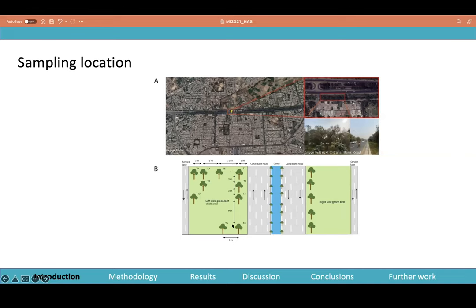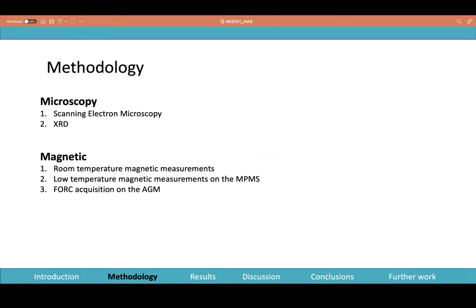You can see the different locations of the trees, but all of them were collected at inhalation height, just because it was easier for me as well to not go through the risk assessments and everything to get a ladder. So the methodology we applied on these leaves was a range of microscopy and magnetic measurements. We started with very basic SEM imaging, which we did at 15 kV to make sure we can image the Fe bearing particles in particular. We did XRD over some powdered leaf samples as well, just to see if there's something else which has gone undetected under the SEM.